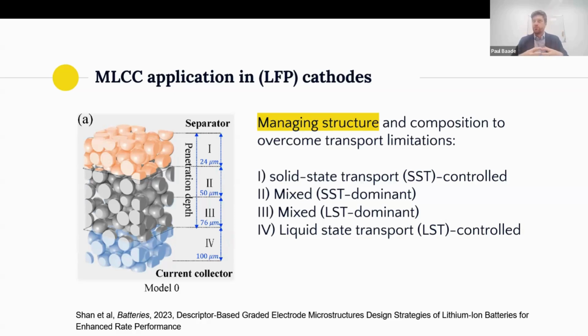And in order to have access or keep access to all of your active material, all of the stored lithium, we need to manage transport by controlling particle sizes across the thickness of the electrode. We can put small particles where they need to be. We can take large particles where they need to be when they're not solid-state transport limited. We can combine them at the right places to tune porosity and ultimately control the liquid-state transport. And what we also allow cell manufacturers and end users to do is to tune the amount of carbon additives to tune electrical transport and minimize the usage of any inactive material.